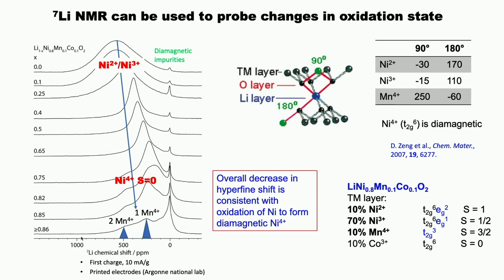So for those of you who've forgotten your inorganic chemistry, nickel 4+ is low spin d6, it's diamagnetic, and the only paramagnetic ions that are in the system are manganese 4+. And when you pull most of the lithium out, the lithium remains near these paramagnetic manganese 4+ ions, and that's why you get these spectra. And so the take-home message is we can actually interpret these spectra. The thing that we can't interpret is in the middle, where things get quite sharp.